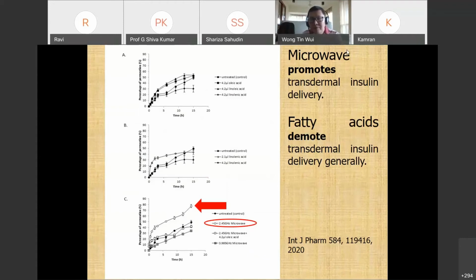We have found that the fatty acids, be it oleic, linoleic, or linolenic acid, demote transdermal insulin delivery instead of promoting it, right? Whereas microwave can promote transdermal insulin to a significantly higher extent than fatty acid. This study is really exciting us because it shows that perhaps with the combined use of microwave and insulin formulations, insulin will be able to be transported across the skin without the need for the fearful injection.